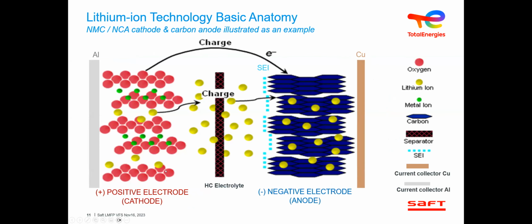So very quickly, the construction of NMC type technology, or NCA, what we call nickel oxide technology. So the very commonly used aluminum substrate onto which basically metal oxides are grafted. So the NMC appears at the atomic level like this, where it offers layers where the lithium is encased. You've probably seen some very good animations of these structures. The lithium, fully discharged, is kept on the cathode side, and when you recharge, with potential, you're migrating your lithium onto the anode side, which is a carbon structure coated onto a copper foil.